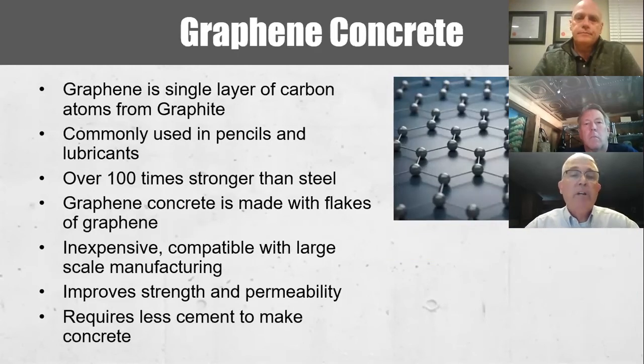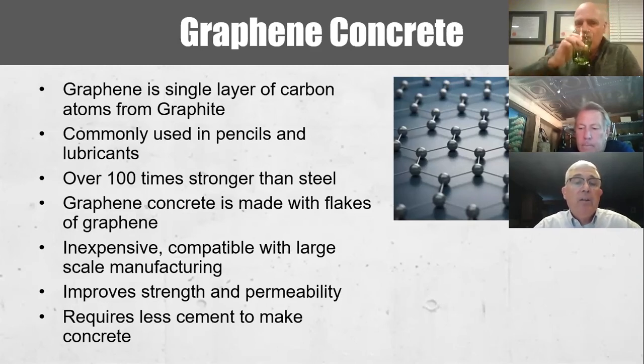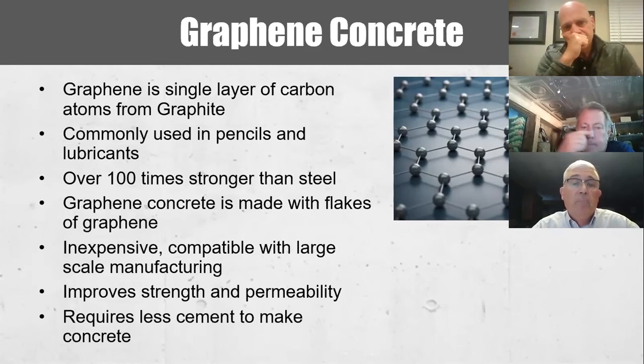Then we have graphene concrete. Graphene are single layers of carbon atoms made from graphite. And graphite is very inexpensive, and this process is capable of large-scale manufacturing. Not yet something that's commercially viable, but being looked at very carefully. So you take these graphene layers, and flakes of it is combined with mixing water to create the concrete that you're going to be using. And it creates very strong and very permeable concrete, reducing the cement component in the concrete very well, suitable for large-scale production applications. So we're watching this very carefully as well.